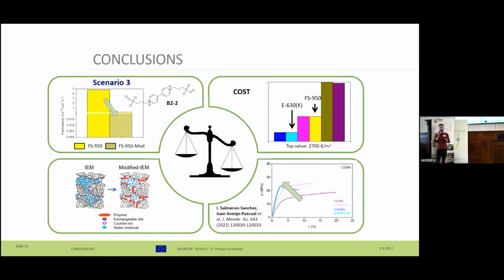Just a brief conclusion. We were asked to foresee a feasible strategy to overcome the problem of the cross-mixing of the active species. And according to our permeability tests, we successfully reduced our permeation rates in most cases. We have made a kind of screening selection of different materials considering very important parameters such as cost, conductivity, and so on. And also I would like to remark that when performing our modification in our materials,